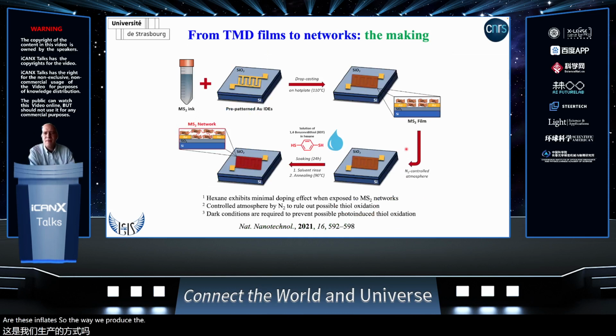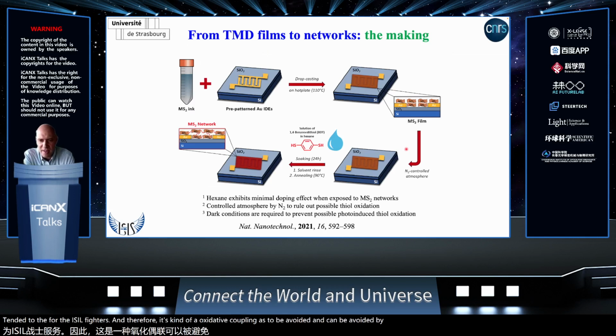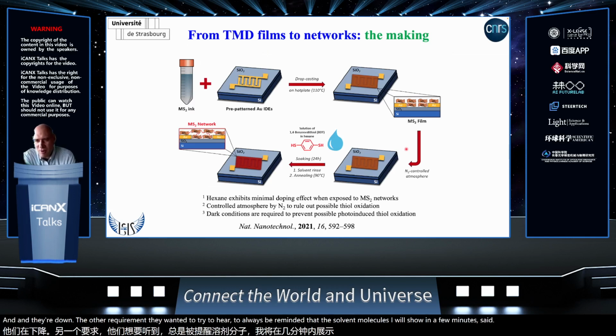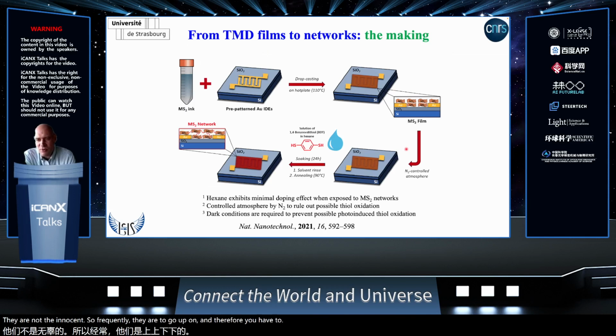The way we produce the film, the network, is actually very simple. We start with the ink and we drop cast the ink onto the interdigitated electrodes. Then we put this in a nitrogen atmosphere and we apply a drop of the doubly thiolated molecule in hexane. What is important is that, as everyone knows, thiolated molecules tend to form disulfide, and therefore this kind of oxidative coupling has to be avoided, and can be avoided by working under nitrogen and in the dark. The other requirement that one always has to bear in mind is that solvent molecules, as I will show you in a few minutes, are not innocent. Frequently they are dopants, and therefore you have to use the most apolar solvent possible. So here we decided to play with hexane.